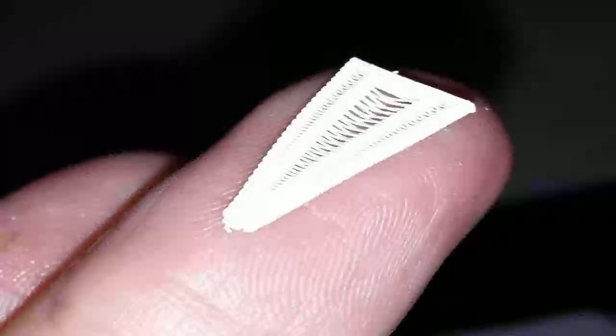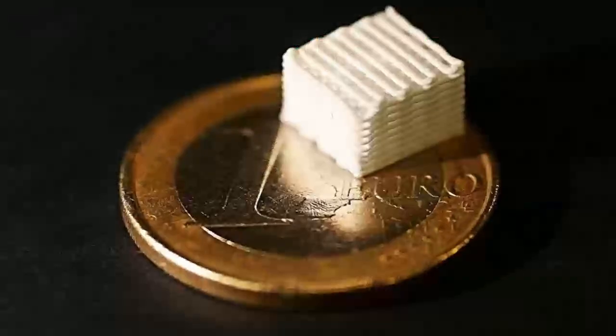Instead of a crack just slicing straight through easily, it's forced to deflect, tilt, or twist to get around the aligned platelets blocking its path. You also get mechanisms like crack bridging, where intact platelets actually span across the crack opening behind the crack tip, literally holding the two sides together.